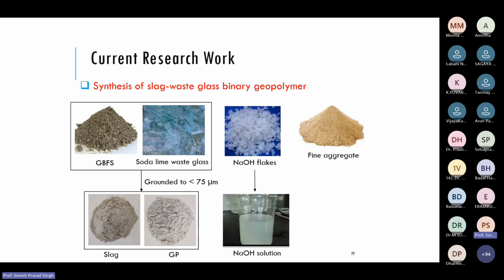And one more thing, if there is excess silica left, once it is subjected to high temperature exposure, one of our concerns is that if our structure is subjected to high temperature or there is a fire, concrete disintegrates. But here, if there is silica left, silica will melt and bridge the gaps, and the residual strength will be higher compared to conventional cement. This is the benefit we observed by replacing 10 to 20% of slag with soda lime glass. So I will tell some select research results.